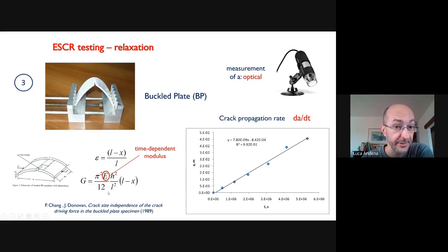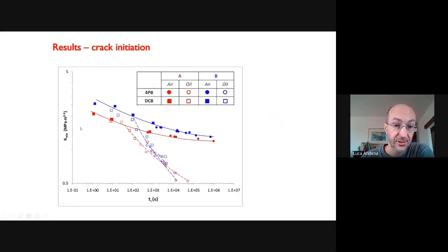And it's constant in the first stages of the test, in which you expect also a constant crack propagation rate. It's hard to detect initiation here, but you can get propagation data. If you look at the results here, these are some examples of these results. You can check some interesting facts. This is the typical outcome of a fracture mechanics experiment to study ESC.